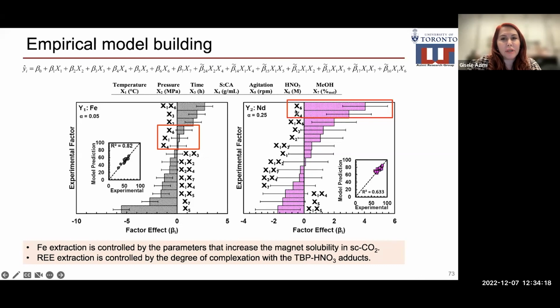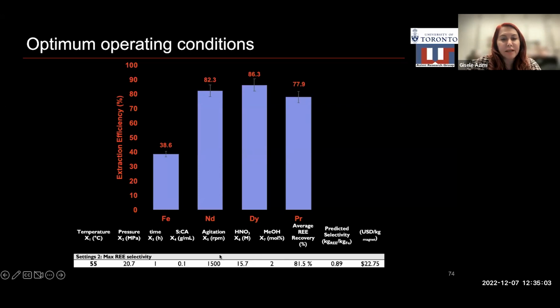Here we see that, for example, for neodymium, X6 and X4, that are the acid content in the adduct and solid to chelating agent ratio, have the most positive impact on neodymium extraction. But these two parameters have no effect on iron, so we can control them to increase extraction efficiency of rare earths by minimizing co-extraction of iron. On the other hand, X3 and X2, that are time and pressure, have the highest positive effect on iron. So iron extraction is controlled by parameters that increase the magnet solubility in supercritical CO2, whereas rare earth extraction is controlled by the degree of complexation with TBP-HNO3 adduct. Under the optimum operating parameters that are shown in this table, we obtain more than 80% extraction of rare earths with less than 40% co-extraction of iron.